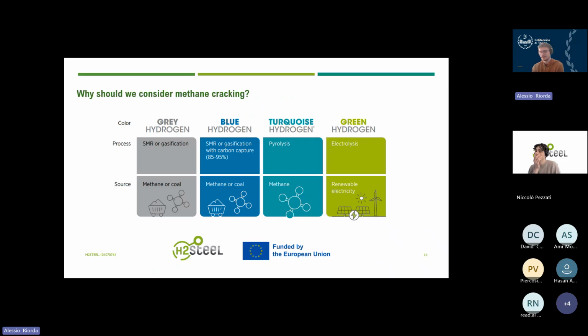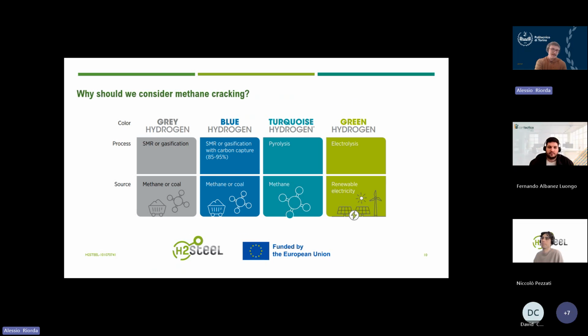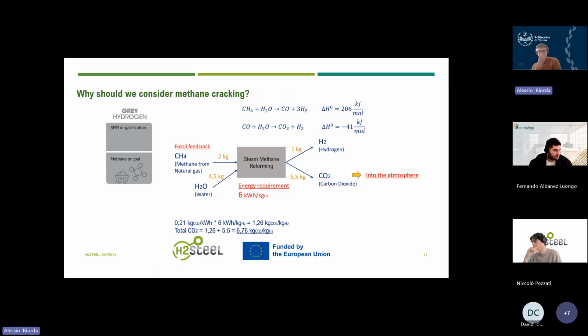And just to conclude, let's see a comparison between different types of hydrogen production routes. Here you can see some of them. Normally the gray hydrogen is produced with steam methane reforming. And the point of this slide is to say, okay, for producing 1 kilogram of hydrogen, you will need 2 kilograms of methane. And the energy requirement will be 6 kilowatt-hour per kilogram of hydrogen produced. And this will lead to CO2 emissions, not only related to the energy requirement, but also from the carbon in the feedstock, which you will transform, of course, into CO2.